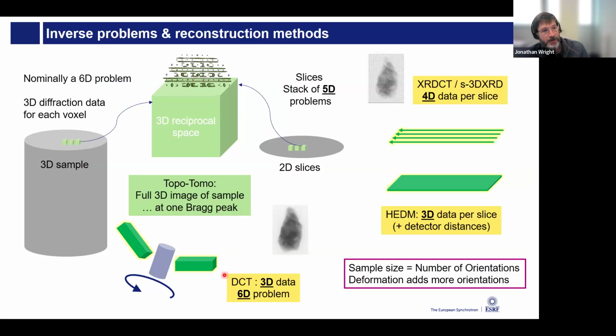The DCT grain maps that I'll show later, you have a 3D data set, and you have this 6-dimensional problem of you need the orientation for each of these voxels. So because it's only 3D data, but with a 6D problem, this works really well when the orientations are quite discrete. So when the sample is undeformed and each crystal in the sample has just one unique orientation, then you can overcome this kind of missing data problem. As the sample becomes more and more deformed, this is especially for metallurgy, but this works in the same way for all the different kinds of samples we see.